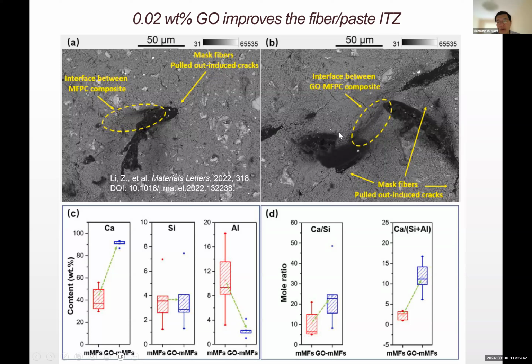Also, when the fiber pulls out, you generate some macro cracks, which also consume some of the fracture energy. And fiber bridging, as we know, is another mechanism to mitigate the freeze-thaw damage or the tensile stress buildup during freeze-thaw cycling. What's interesting is that when you treat the fibers with this dark ink, or graphene oxide, the cement chemistry changes. I should say the hydration products near the surface of the fiber are different than without the graphene oxide treatment. For instance, especially for the calcium and aluminum, it is significantly different if you look at the box plots. And then, of course, another way to look is the elemental ratio.